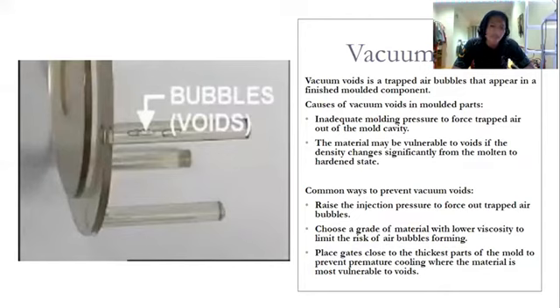The material may be vulnerable to void if the density changes significantly from the molten to hardened state. So the best way to prevent the vacuum void is by raising the injection pressure to force out the trapped air bubble. Next is to choose a grade of material with lower viscosity to limit the risk of air bubbles forming. And lastly, place the gate close to the thickest part of the mold to prevent premature cooling where the material is most vulnerable to void.